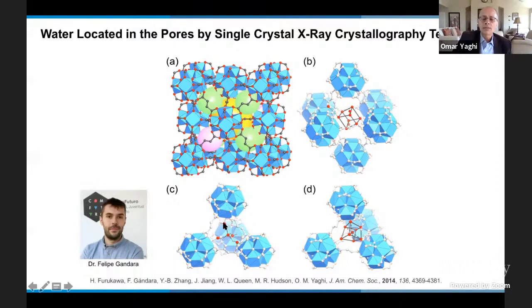So you see here for this MOF, we found the water molecules shown here in red bound to the metal oxide unit, or to the inorganic unit. And then as more water comes in, they make up aggregates such as these cubic aggregates. And these, we find, are the seeds onto which other water molecules come in and bind.